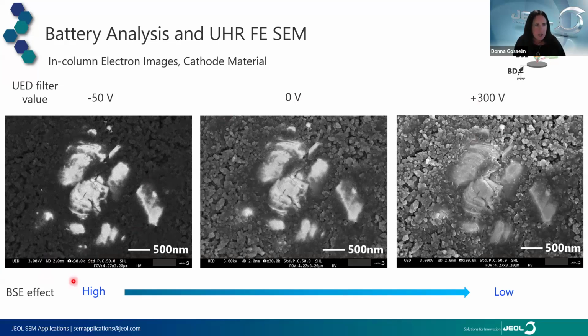is something with more compositional contrast. So the gray scales are showing us what's different chemically within the material. We need our EDS detector to tell us what, but at least we can say we see differences in the chemical composition. Going the other way, applying a positive voltage, now we're collecting more of those low energy electrons. This is giving us much more surface detail or surface characterization. Okay.